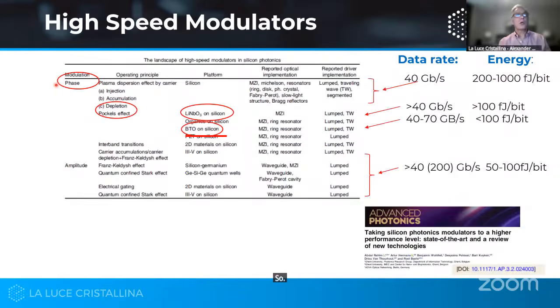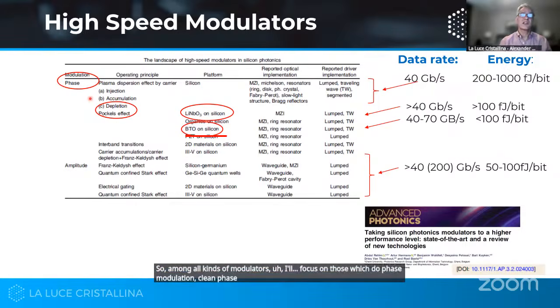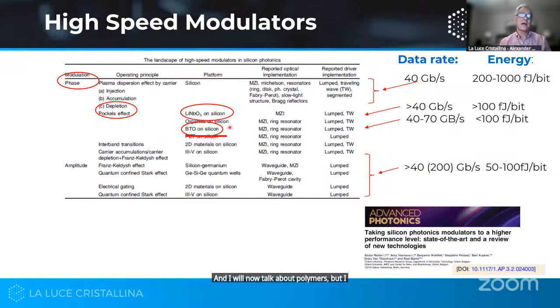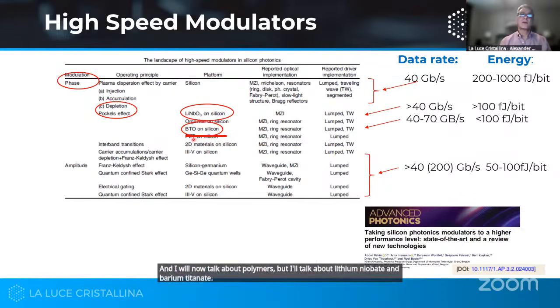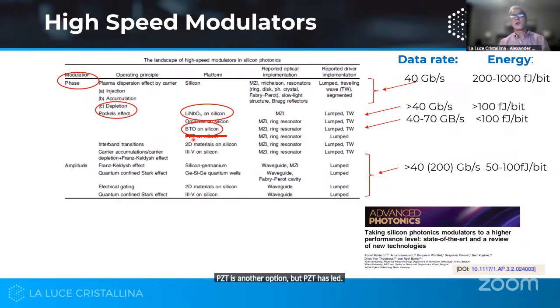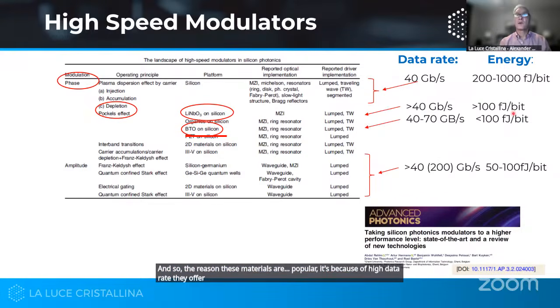So among all kinds of modulators, I'll focus on those which do phase modulation, clean phase modulation. So they're essentially phase shifters in various forms, and they use Pockels effect. I will not talk about polymers, but I'll talk about lithium niobate and barium titanate. PZT is another option, but PZT has lead, and so this is a no-no. The reason these materials are popular is because of the high data rate they offer and low energy of switching. So they allow a low energy solution, which is attractive for data centers.